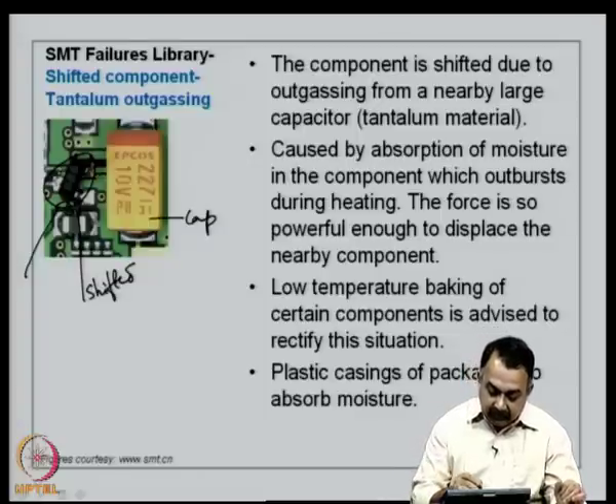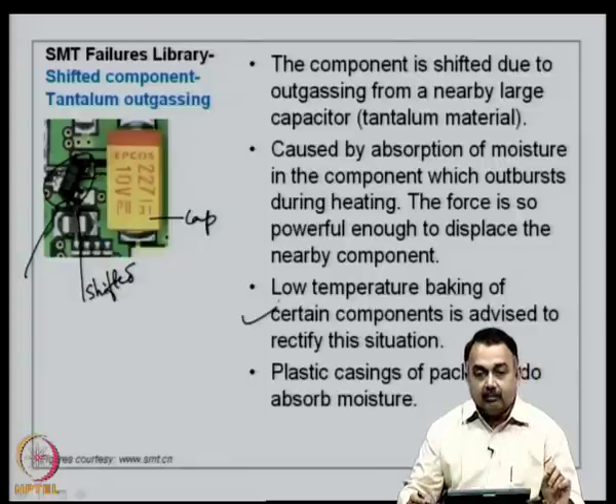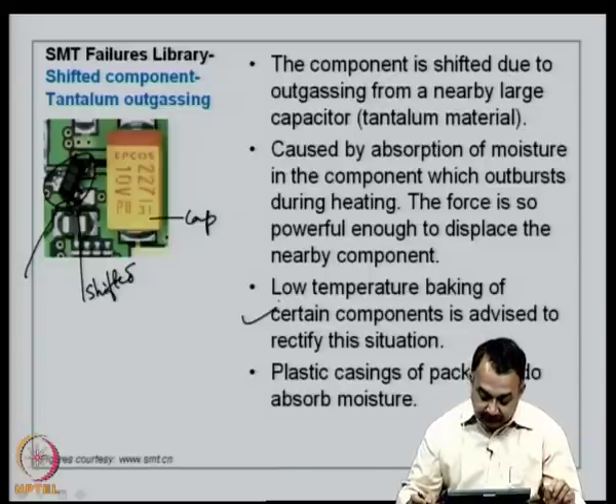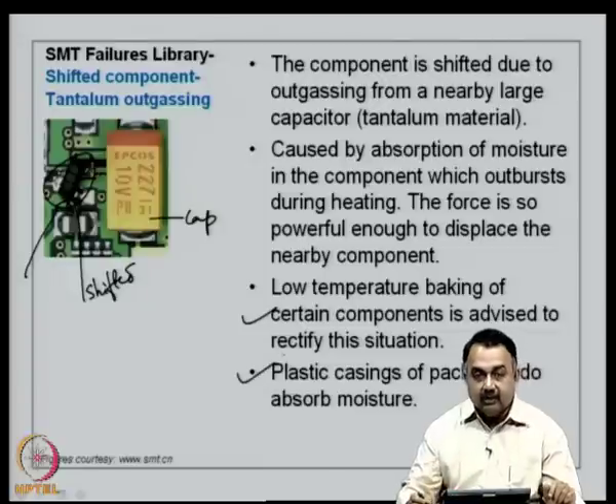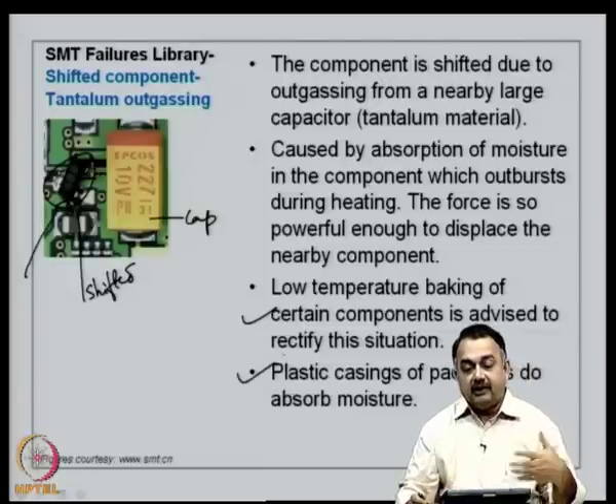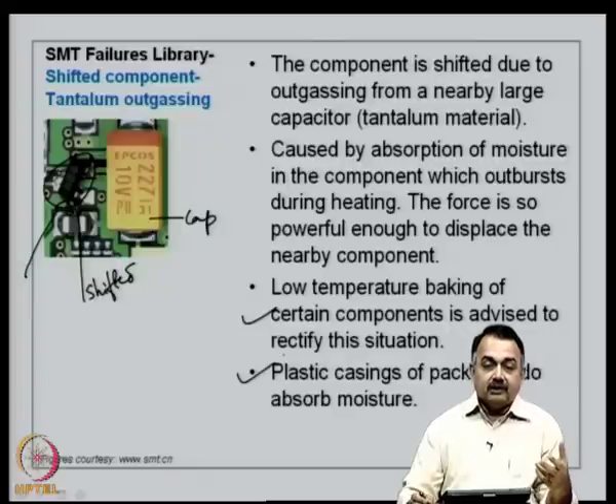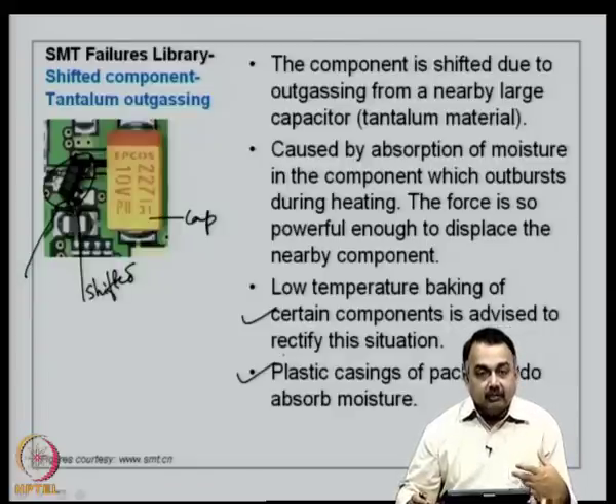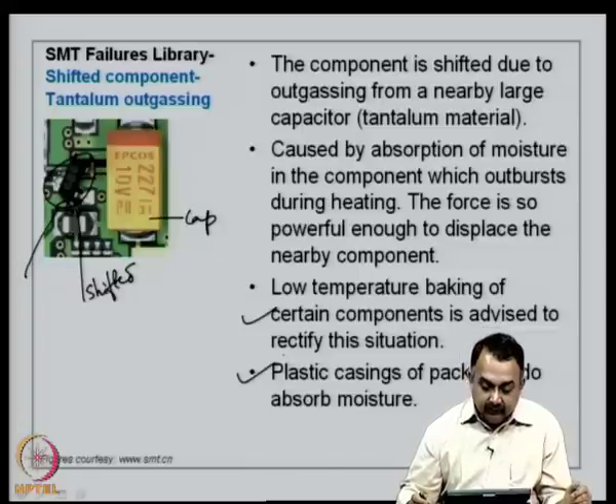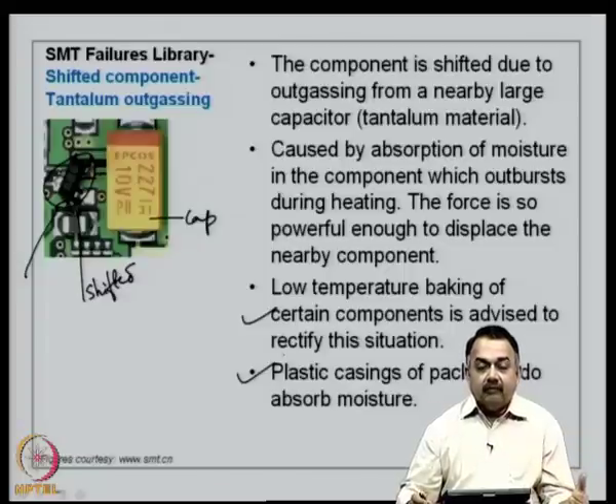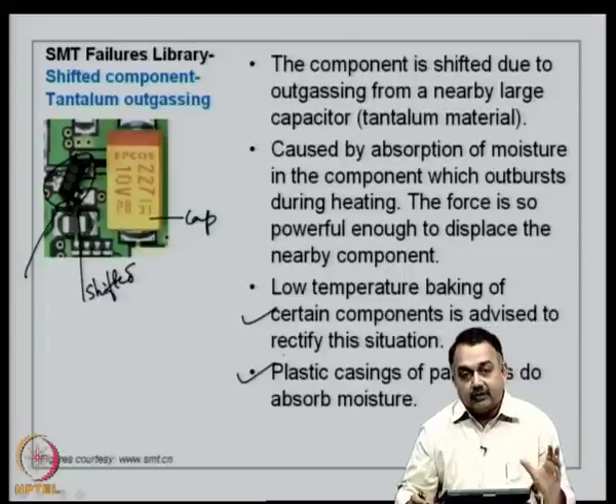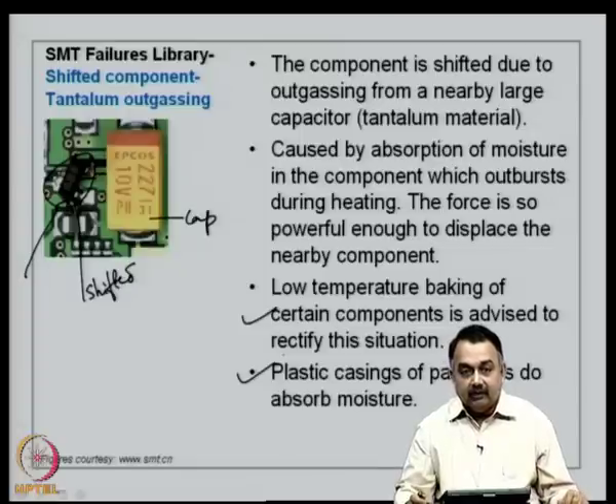So, it is very easy to displace the nearby component if it is lightweight. So, low temperature baking of certain components is highly recommended for these kinds of outgassing defects. And plastic casings of packages do absorb moisture. So, if you look at the datasheet of packages, you necessarily have to look at this problem, because this is a global phenomenon. Many defects have been seen due to moisture absorption by packages, especially large packages like this capacitor. Therefore, you have to do a pre-baking before you actually send them to a reflow soldering process.